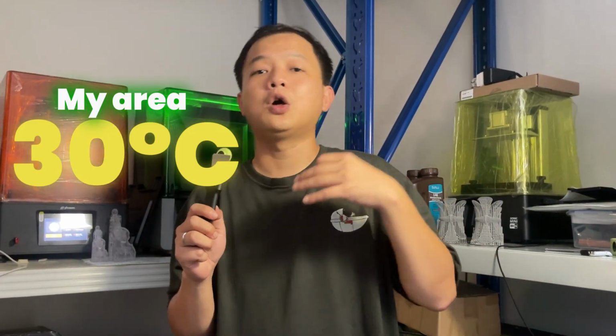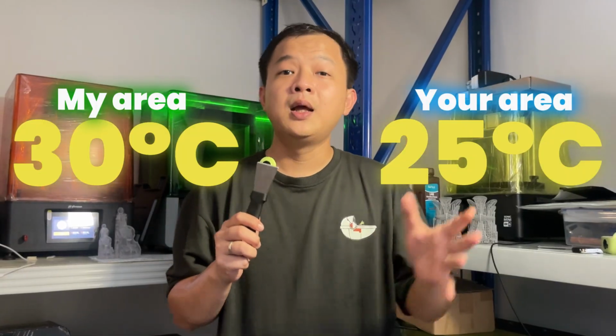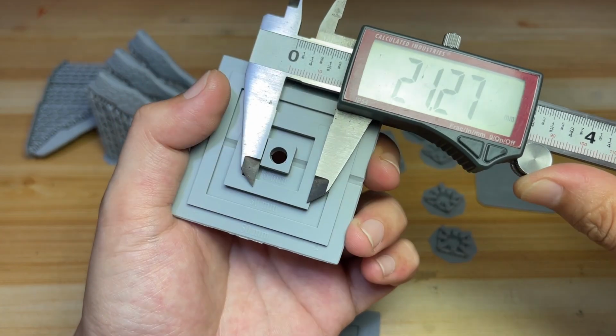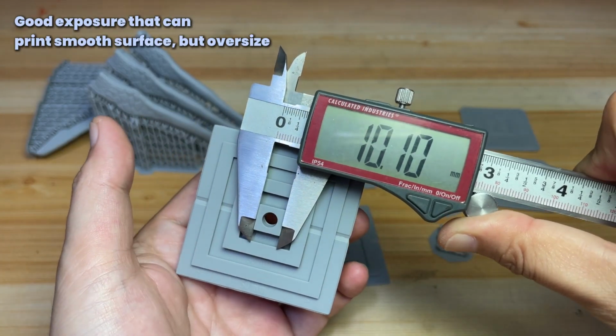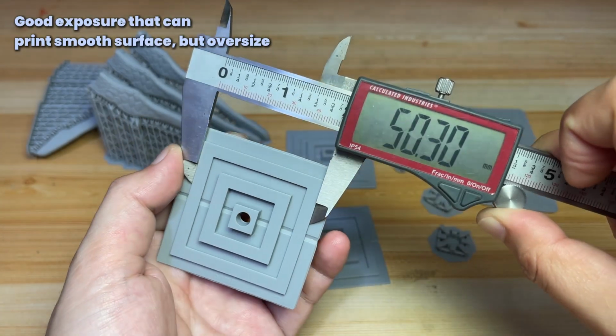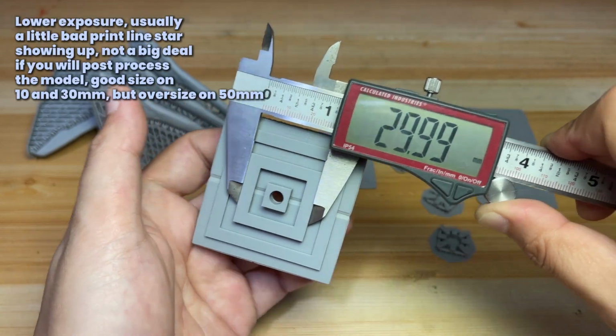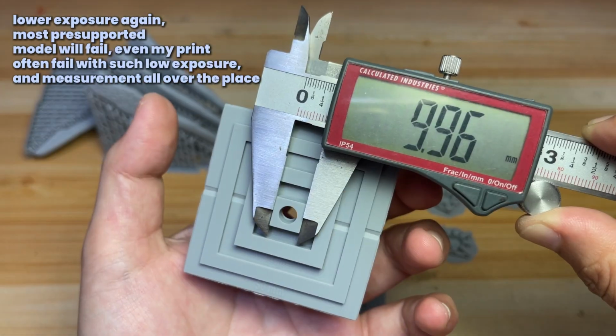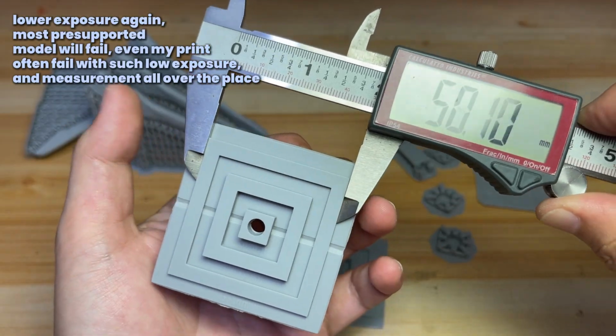For example, let's say you and I use the same resin, same printer, and same everything. I live in a tropical area with an average temperature of 30 degrees, and you live in a slightly colder area, with an average temperature of 25 degrees. My optimal exposure, let's say, is 2 seconds, and luckily I have accurate dimensions. Your place is colder, so you need slightly longer exposure, let's say 2.4 seconds. Because your exposure is 0.4 seconds longer, that means more time for light to spread. You end up with slightly larger dimensions due to the longer exposure. Because you want to achieve accurate dimensions, you lower your exposure and you get failed prints like delamination because you end up underexposed.